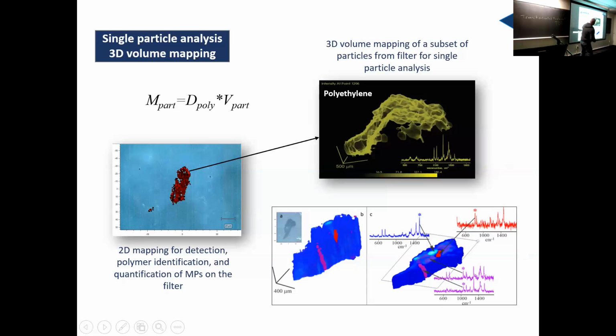So what I do is the 2D mapping is exactly the same, but I can go up using layers. And now I can create a 3D image of that small particle. And that is important because, for example, this particle was around 500, 600 micrometers, and you can see different colors, and those different colors represent different polymers. So this particle was made of different polymers. We have polypropylene and polyethylene here. This is polypropylene, this is polyethylene.